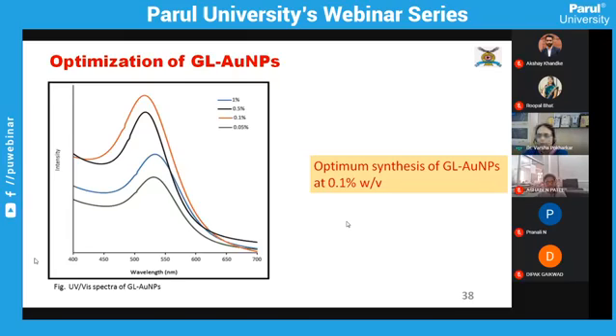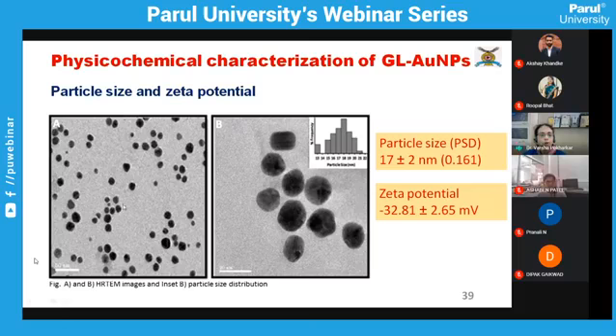So you can see how little of the reducing agent is required for the preparation of the gold sol. Further, the high resolution TEM images showed that the particles were spherical in nature and the particle size obtained was around 17 nanometers, and in the inset you can see that it is a pretty narrow distribution that we have obtained, and the zeta potential was around minus 32 millivolts.